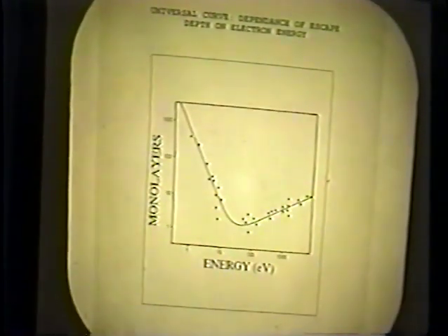In that way, we very fast stop the exit of the electrons. This is the universal curve for the dependence of escape depth on electron energy. This is a graph you can find in any textbook about XPS, and those here are more organic compounds, polymers; this part corresponds more to inorganic elements. What we have really is placed somewhere here: zinc, platinum, palladium, somewhere between 50 and 150, 200 electron volts energies. That means we have a maximum depth of escape somewhere around 5 monolayers, which corresponds to 10 to 20 angstroms for different elements. It is a pure surface technique. We just see the surface, nothing other.